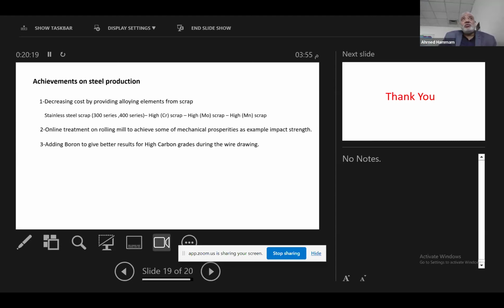We are aiming now to work on online treatment in the rolling mill to achieve the same mechanical properties without going to a post heat treatment. This is under upgrading now in order to reach the same level for some grades. We succeeded in achieving the impact test by controlling all the parameters on the mill line itself, without going for further heat treatment.